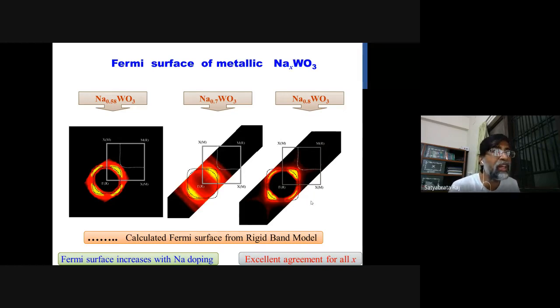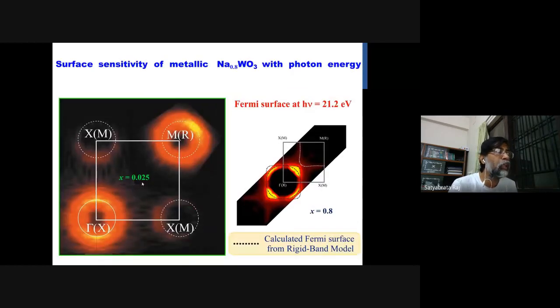But if we measure the insulating one, the insulating sample should show a Fermi surface around the gamma point, not at the X or M point. But the insulating feature shows a Fermi surface at the X and M points. So it's possible that these are surface reconstructions, but we don't see any surface reconstruction at this energy. So we would like to see the surface sensitivity of the metallic sample with photon energy. So what does it mean?